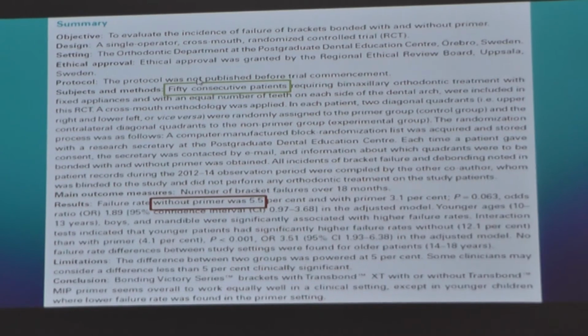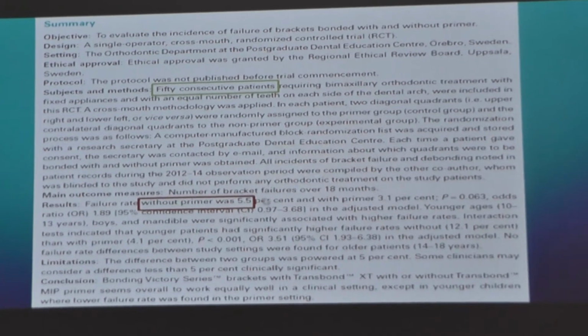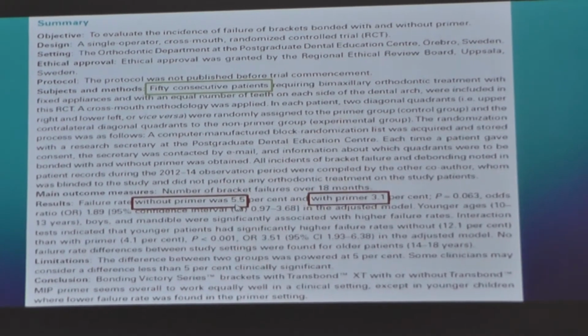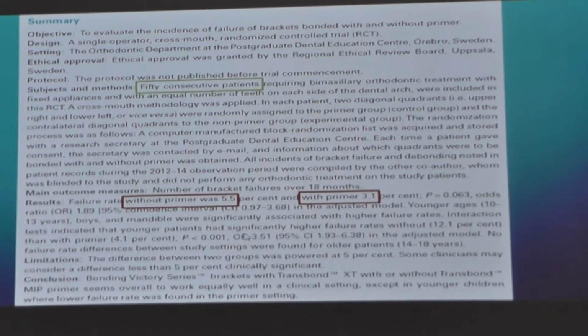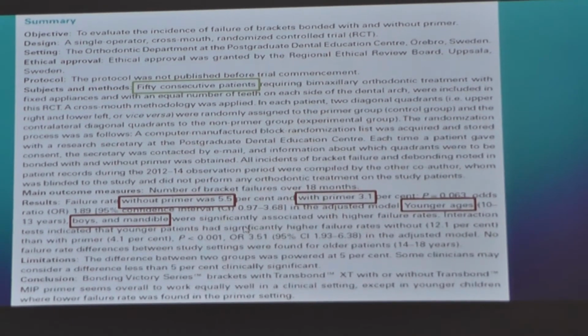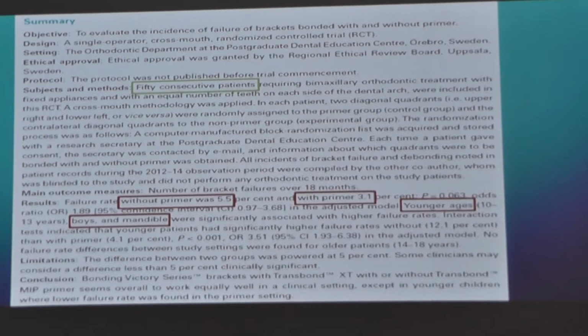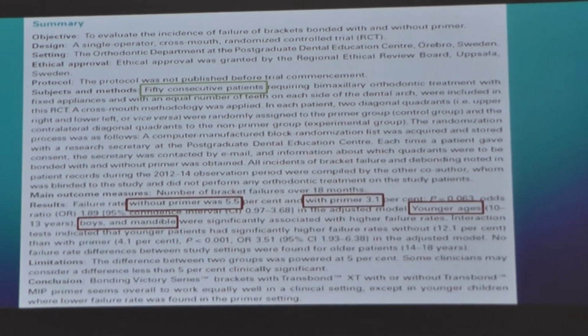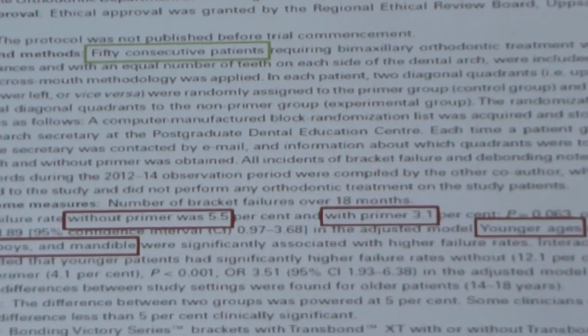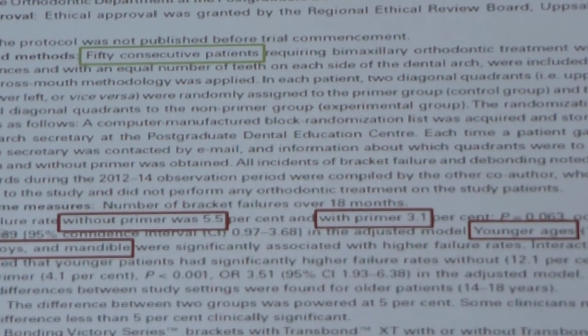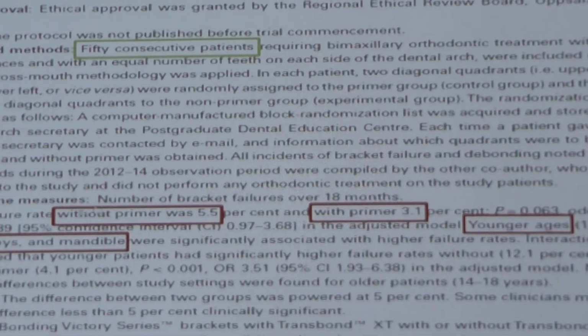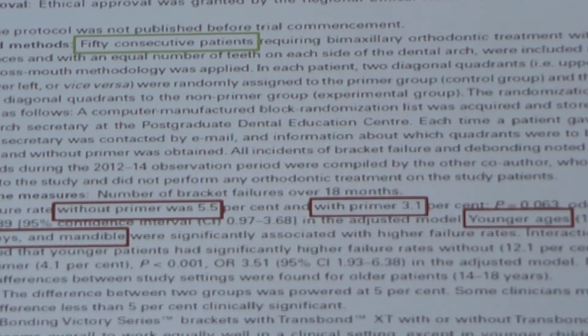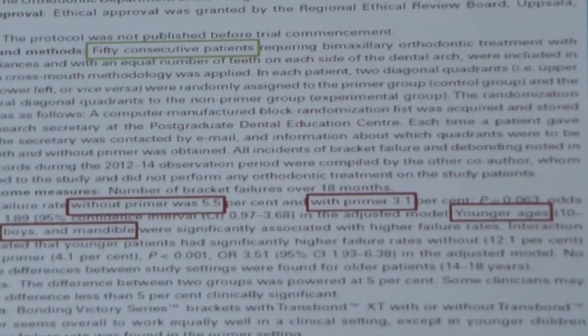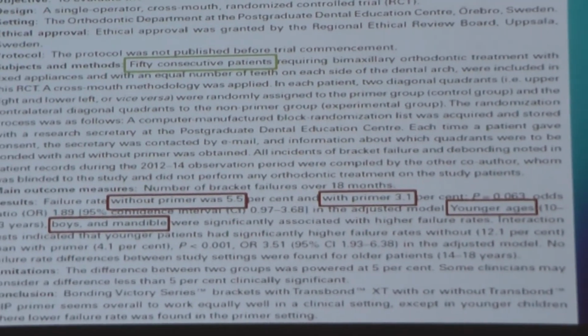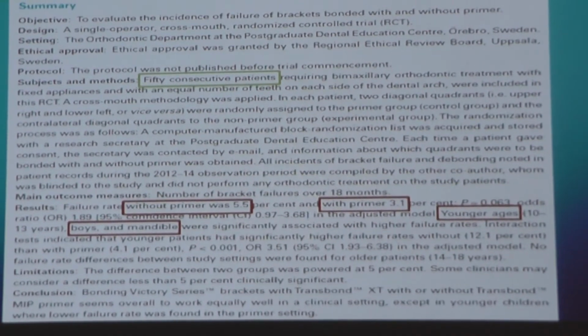So they treated 50 subjects, and they saw that the failure rate without primer was 5.5% and with primer 3.1%. It was not statistically significant because they powered the study at 5%, but clinically it could still mean a significant difference, because you can see that the odds ratio of failure if you do not use a primer is almost double compared to when you use the primer.